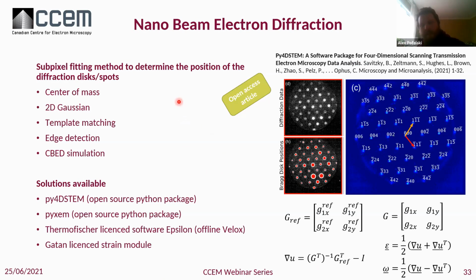It's going to be slightly better in comparison to the real space method, because you can play on, for example, the camera length to space the spots at different distances. But in general, you want to add a subpixel fitting method to determine the position of the diffraction disks or spots. And so again, we come to the same area where there are lots of different solutions: center of mass, 2D Gaussian, template matching, edge detection, or you can even make a simulation and try to overlap it with the pattern that you have. And each of these solutions will have slight differences.